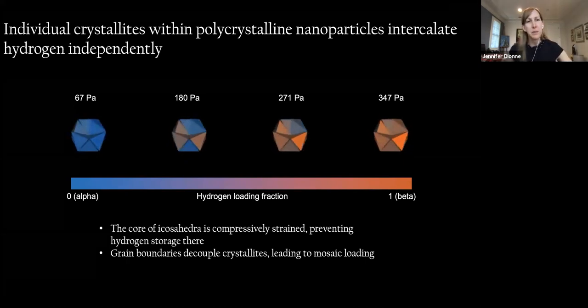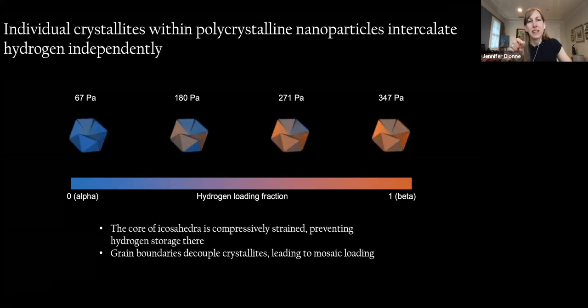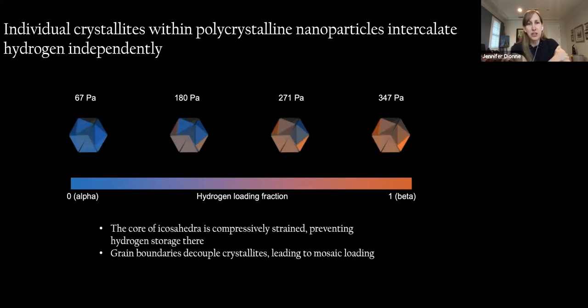We can also look at individual crystallites within the icosahedra, and here, just in the interest of time, I'm skipping over how we do the experiment. But we have essentially tetrahedral crystallites that comprise the icosahedra, and we can look at diffraction to identify how each tetrahedral component of the icosahedra has transformed in equilibrium conditions. And we wind up seeing that essentially the grain boundaries decouple the crystallites, leading to what we've called mosaic loading. So when one tetrahedral crystallite transforms to a hydrogenated phase, that basically applies strain to the neighboring tetrahedra, making it a little bit harder for the neighboring ones to transform. So you have to get up to much higher pressures to enable complete transformation to the beta phase.